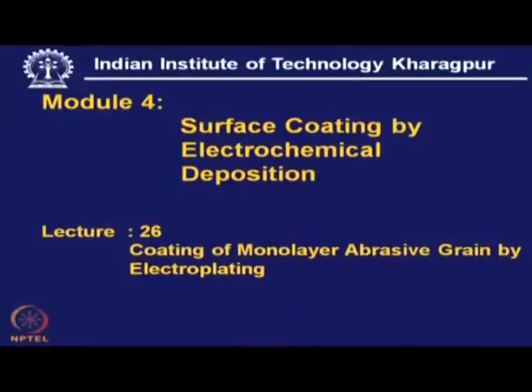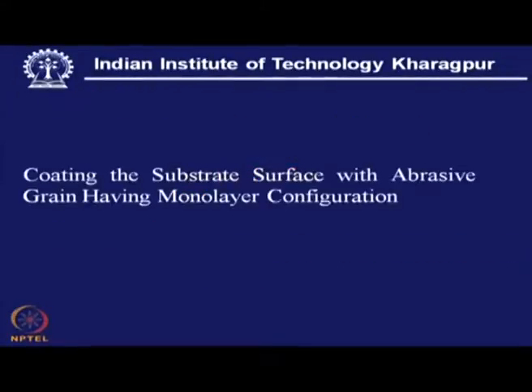Coating of monolayer abrasive grain by electroplating, and this happens to be a very special application of surface coating by electrochemical deposition. So, it exactly means coating the substrate surface, it can be a metal or hard metal or even ceramic, and in this case the grains have a monolayer configuration, and these grains will be anchored by an electrodeposited metal around each grain.